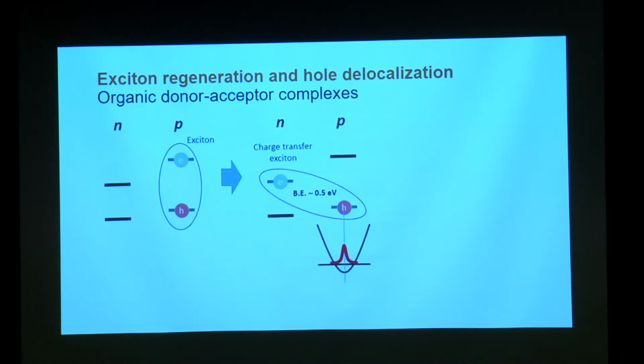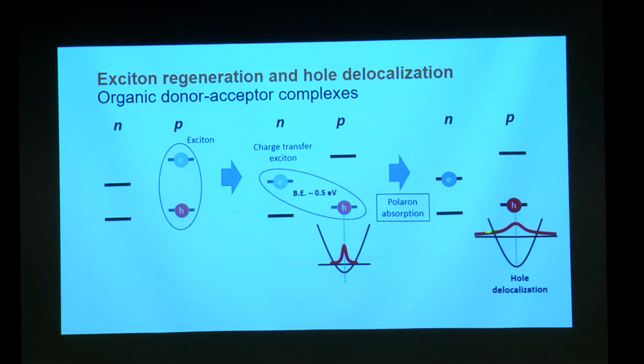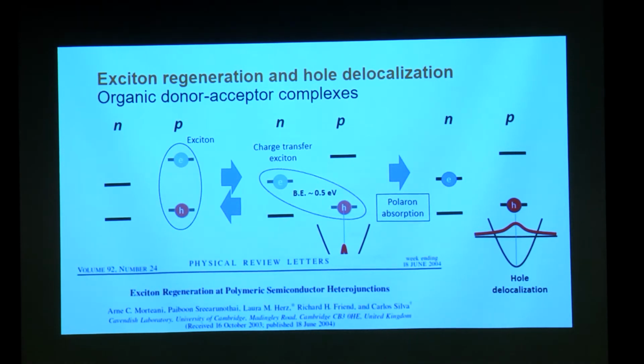The more or less accepted phenomenon is that when this particular thing is formed, the hole is in a strongly localized state. And that hole essentially absorbs polarons and goes into a slightly higher energy, delocalized hole state. When the hole delocalizes, it screens the electron-hole interaction, and that gives you the free electron, and that free electron conducts electricity. So the delocalization of the hole seems to be the reason why a solar cell works in organic semiconductors. Another process that can work here is that the charge transfer exciton can go back into the excitonic state, and that process is called exciton regeneration. So there are two processes that can happen. One is exciton regeneration from a charge transfer exciton, and the second is hole delocalization that leads to a free carrier in the system.